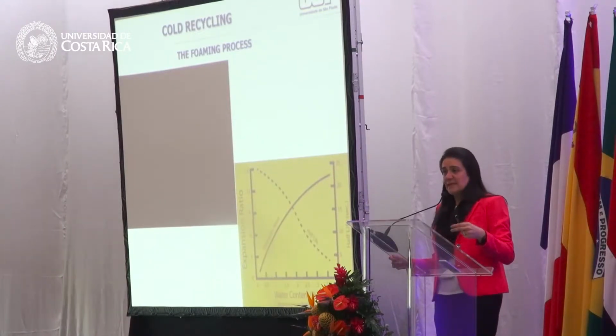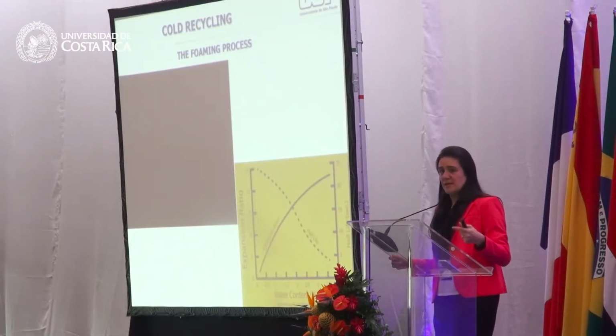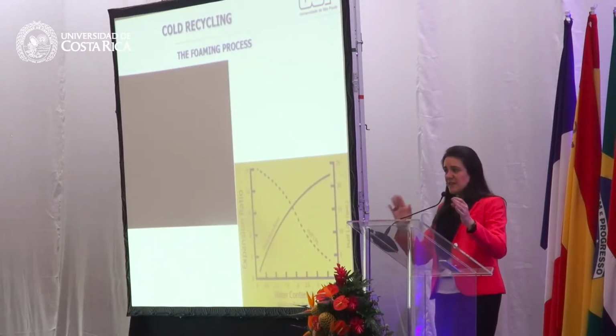The expansion ratio is related to how much I have increased the volume of the initial material. So the higher this number, the better for me. So we normally design the mixture facing these 2 parameters.